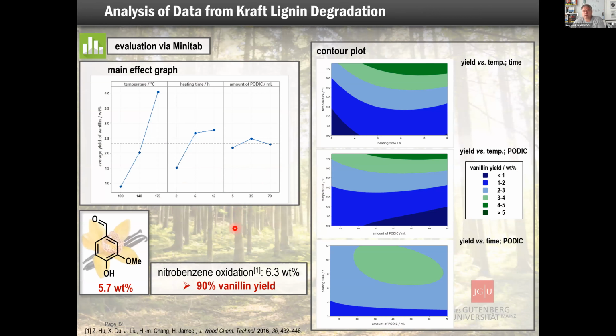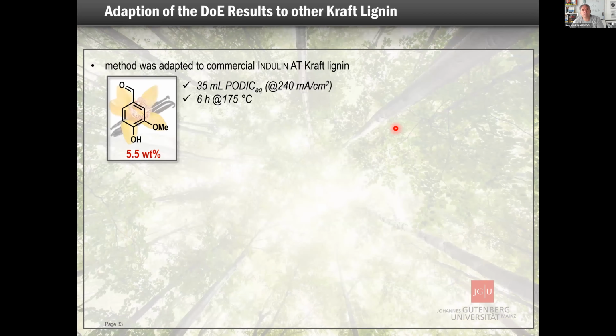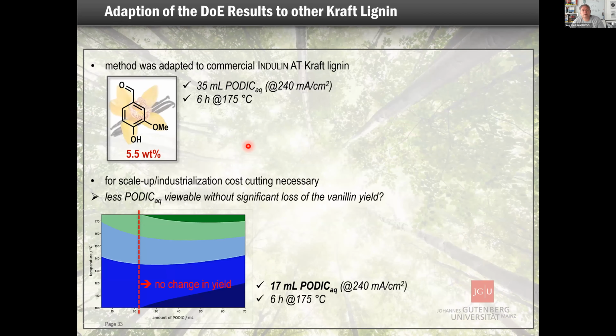The optimization was then done by design of experiment, and then you can go even higher with the amount. You need less of the corresponding PODIC. Here you see the yield, and if you look a little bit more in detail, you see this is the highest yield, and you can go to the lowest amount of PODIC to get still 5.5 weight %. And in this way, you are able to make it in a very efficient way.